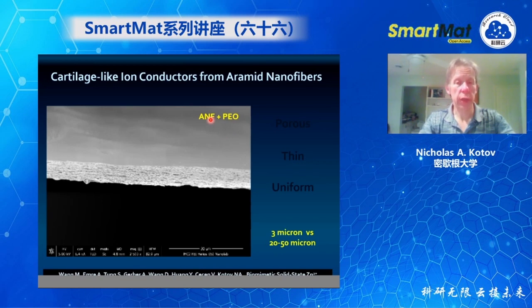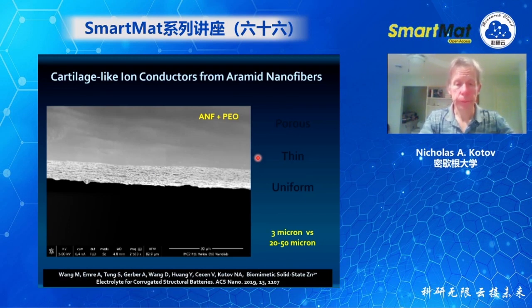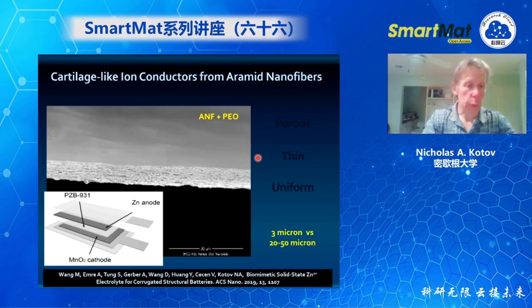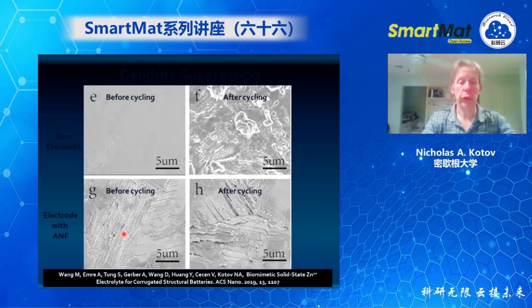Here we used a combination of aramid nanofibers, also made in a cartilage-like structure, quite thin. It is 3 microns. It's also porous, thin, and uniform. In this case, it was with polyethylene oxide. We made the classical zinc anode with manganese oxide, not the best cathode, but it'll enable us to show the proof of concept.